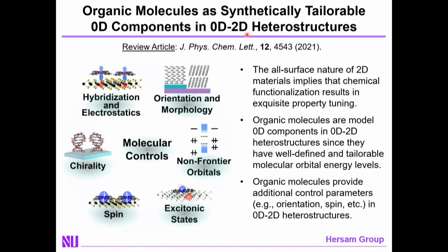And so the question is, what zero-dimensional system are we going to look at? And there are many possibilities. We could look at quantum dots, for example. But in our lab, we generally use organic molecules as the 0D component. And the reason is that organic chemistry allows us to synthetically tailor the properties of the 0D component, for example, the HOMO-LUMO gap. This, of course, is also enabled by the fact that the all-surface nature of 2D materials implies that any chemical modification, such as an organic add layer, will enable exquisite property tuning in its own right due to changes in the local dielectric environment.